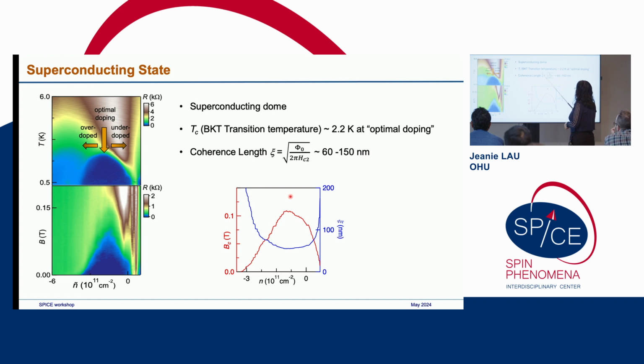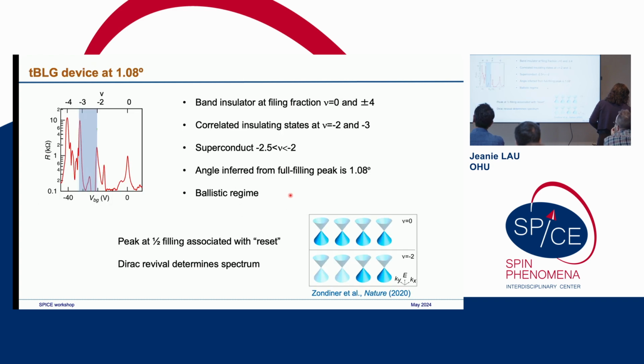And the coherence length is related to the upper critical field. Again, we define this at 20% of normal state resistance, and it's about between 60 to 150 nanometers. So again, all of this agrees with previous reports. It's just a really nice sample with relatively higher TC.